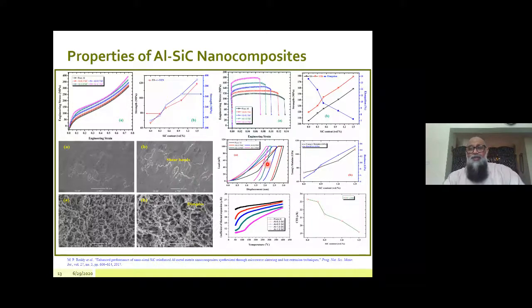A similar behavior we found during nanoindentation. All the developed nanocomposites were tested under a constant load of about 100 millinewton, and we studied the depth of penetration. We can see that the depth of penetration decreases with the increasing amount of silicon carbide content in the matrix. And you can see that the hardness and the Young's modulus increase with the increase in silicon carbide nano content. Why is there an improvement in mechanical properties like hardness and strength with the increasing amount of silicon carbide content in the matrix?